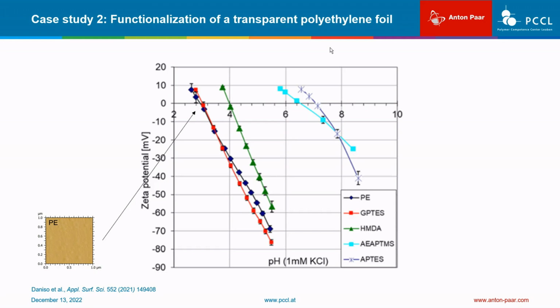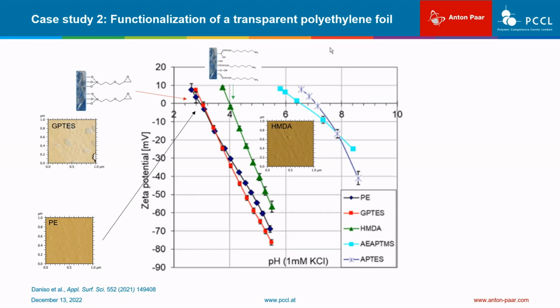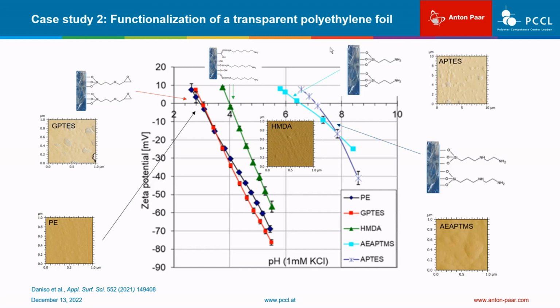We checked the surface with atomic force microscopy and could see a difference in the topography. Attachment of HMDA on the polyethylene surface leads to a pH close to 4. From this result, we conclude that the reaction was not perfect. Some remaining negative groups could be detected. In case of the attachment of the amine-terminated silanes, we could distinguish the surface by the amount of positive charges. The isoelectric point of the amino-ethyl-aminopropyl silane was highest and close to pH 7.